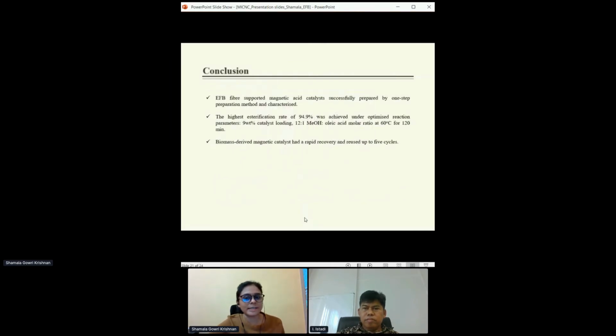In conclusion, the EFB fiber supported magnetic acid catalyst was successfully prepared by the one-step impregnation method and characterized by various analyses. Based on the optimization results, we found that the highest esterification rate of 94.9% was achieved at the optimized parameters of 9 weight% catalyst loading, 12 to 1 methanol to oleic acid molar ratio, at 60 degrees Celsius for 2 hours of reaction time. The biomass-derived magnetic catalyst can be separated easily and reused up to 5 cycles.